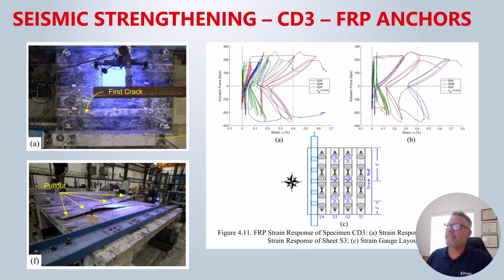This specimen, CD3, or cantilever diaphragm number 3, is using the CFRP bonded laminates anchored with the traditional FRP anchors. There were many different configurations used, but this is a good depiction to compare, where you have, again, the bonded laminates and then anchored at the termination points with the FRP anchors, but then also along the length, a very robust anchorage plan using the traditional FRP anchors.